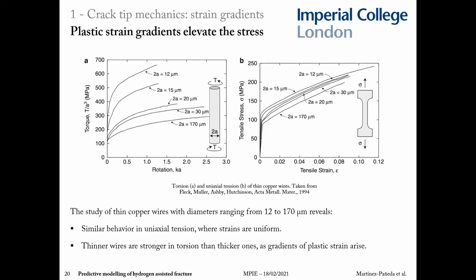This has been consistently observed in a number of microscale experiments from indentation to bending, but the ones that I like more are the torsion experiments by Fleck and co-workers. What you see in the slides are experiments done on thin copper wires, torsion on the left and uniaxial tension on the right. And you can see that in uniaxial tension, where strains are uniform, the response is roughly the same independent of the size of the wire. However, in torsion, where plastic strain gradients are present, the flow strength can be 4 or 5 times higher for thinner wires than for thicker wires. So you have geometrically necessary dislocations that develop to accommodate the lattice curvature, and this leads to a stress elevation.